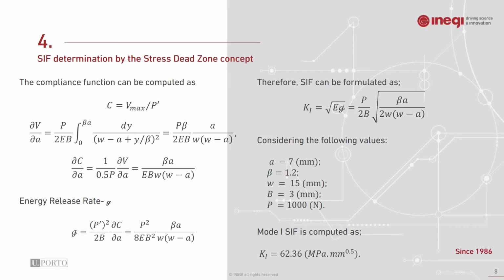In this slide, the stress intensity factor is going to be calculated by the concept of the stress dead zone, and so the vertical displacement has been formulated in the previous slide. It is going to be used here in the integration and in the derivative in terms of the crack length, and according to the energy release rate, it is possible to formulate the stress intensity factor mode 1 as can be seen on the right side, the first equation.